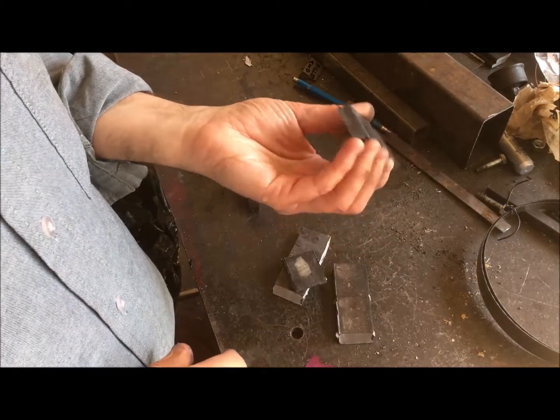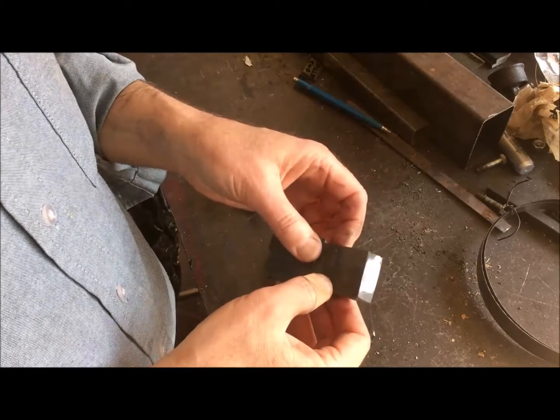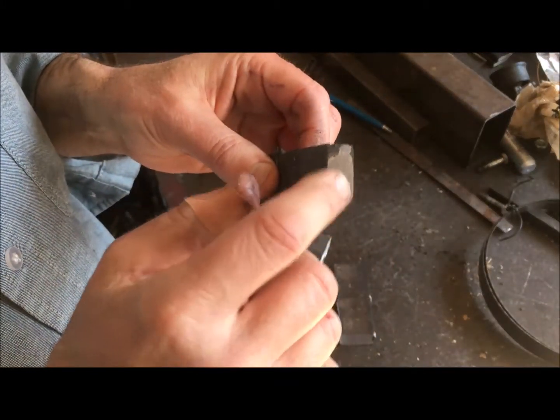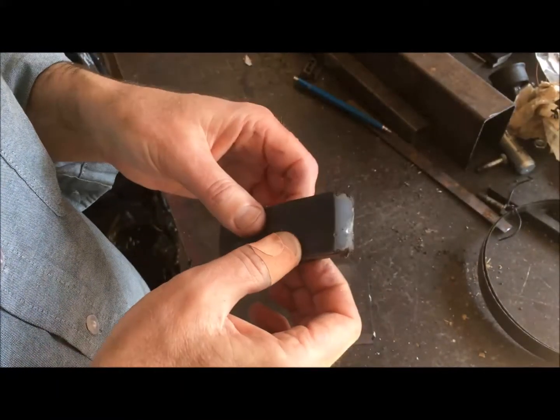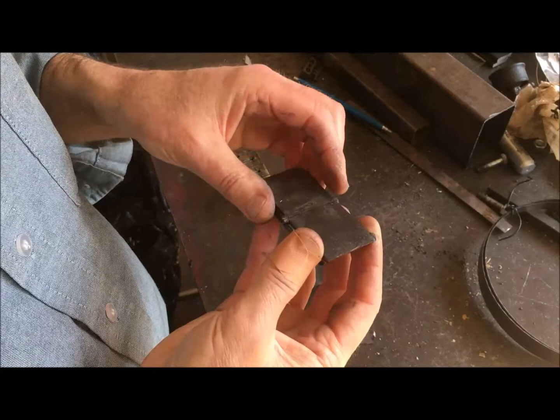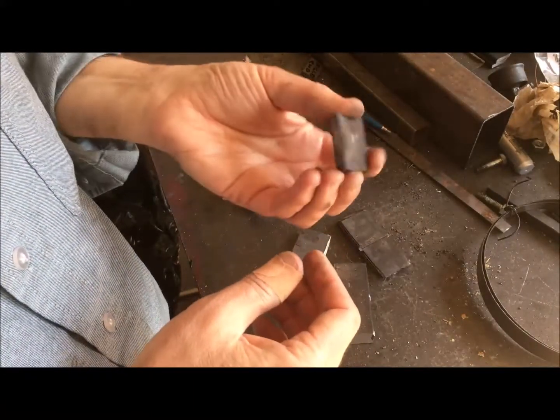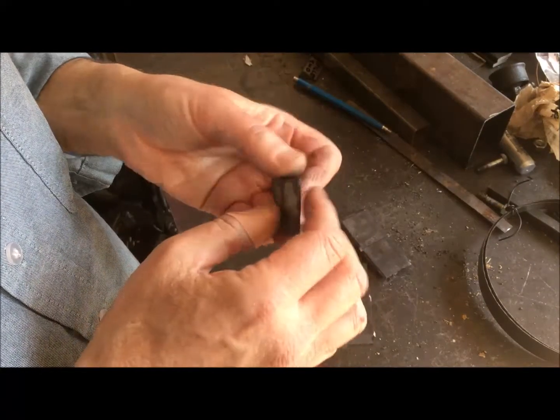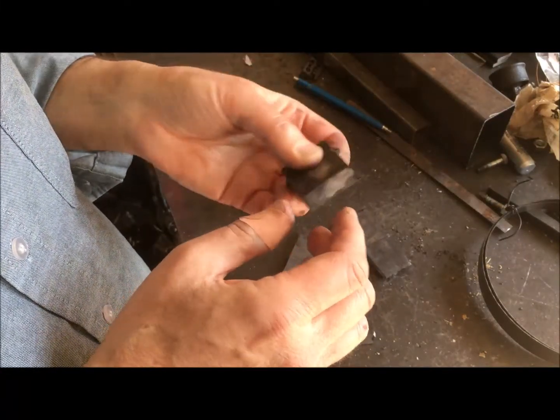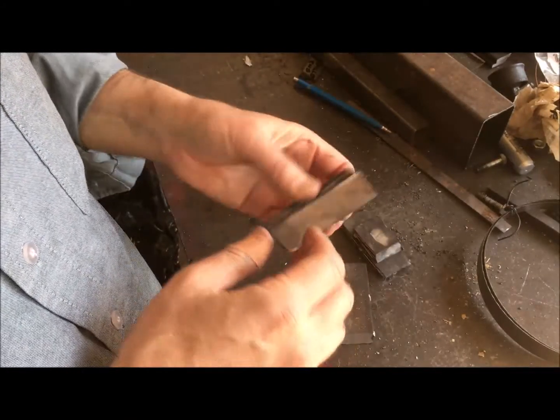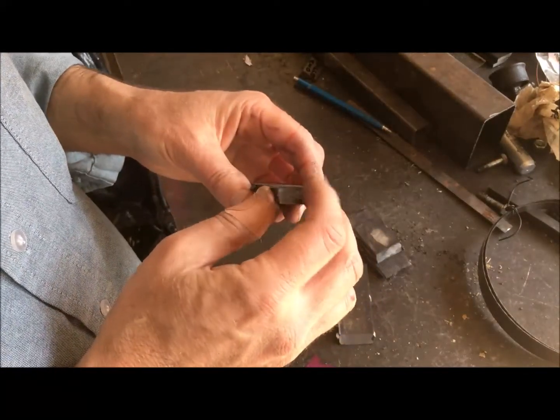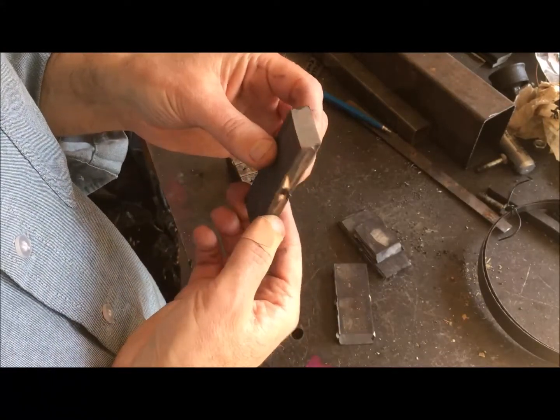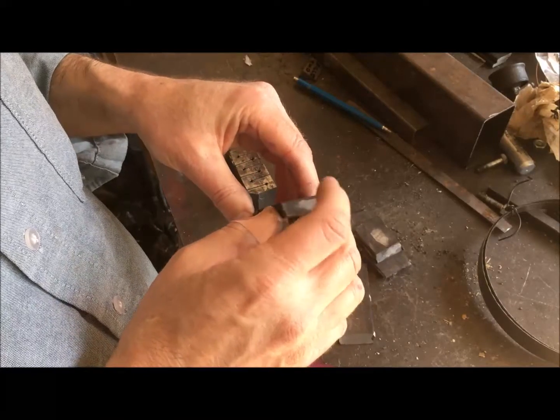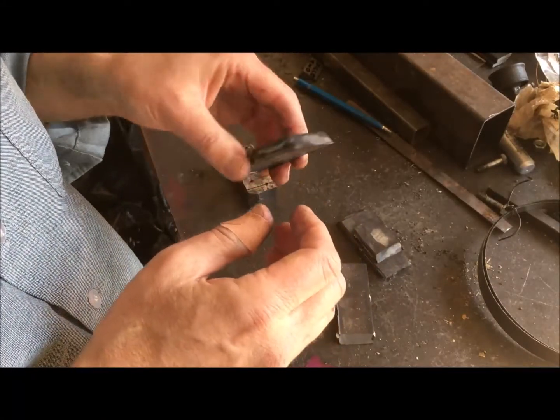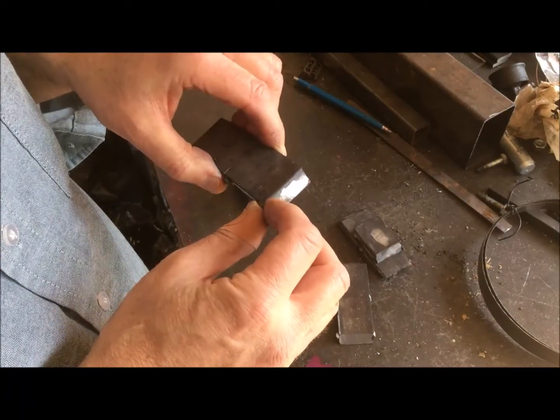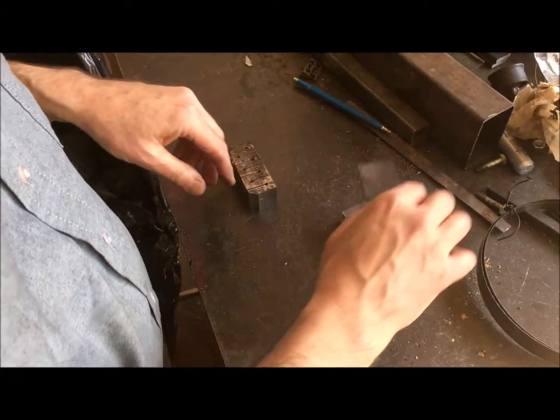Finished the welding heat, and that didn't work. You can see how it got a little bit of weld going on the edges there maybe, but really no. I think that what happened was that I had put a couple of pieces of hard fire brick in the bottom of the forge to protect the bottom of the forge from abrasion and flux, and that brick was not reflective. It was dark colored, and I think it absorbed enough heat that the thing just didn't quite heat up enough. So anyways, I'm putting that aside for the moment.